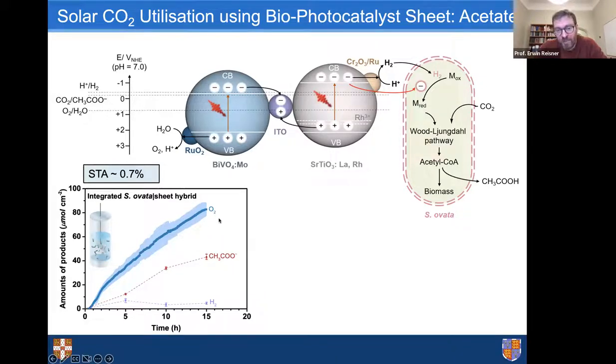I should also say here that this required even more optimization because this bacterium is actually quite oxygen sensitive. So it was important that the oxygen concentration in the headspace was kept as low as possible to make sure we are not damaging the bacteria that produce the acetate.